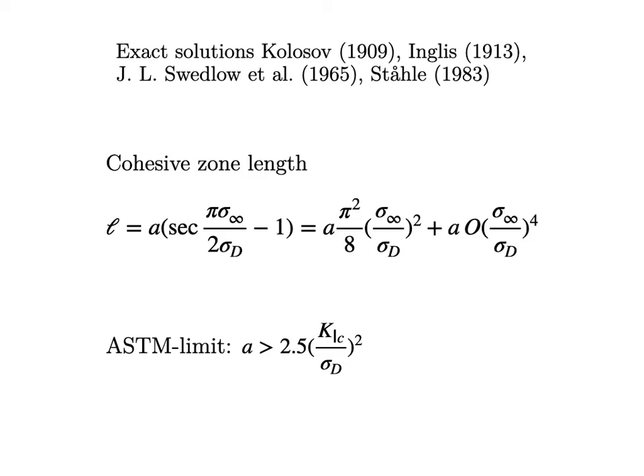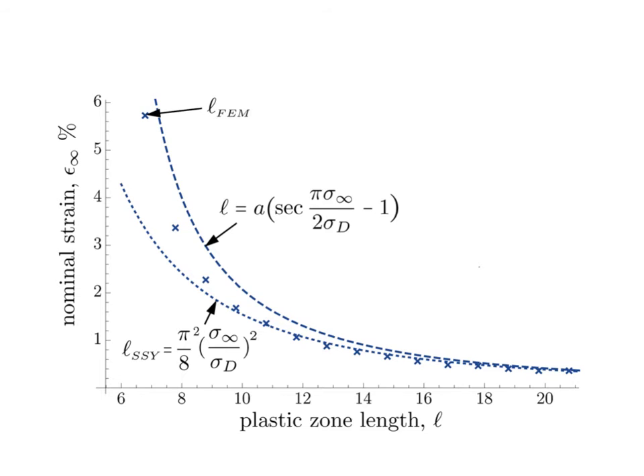This graph shows the length of the cohesive zone as a function of the remote stress and the cohesive stress. It shows the expressions both for large scale yielding and small scale yielding. Here the finite element result, the cross markers, are compared with the exact result for a large cohesive zone, including a small one, and the small scale yielding approximation, the lower dotted curve. The first one is the dashed curve.